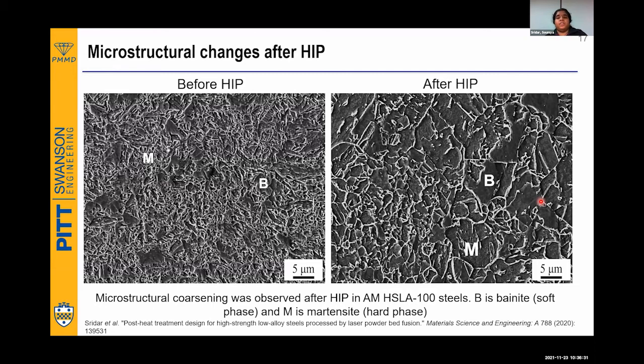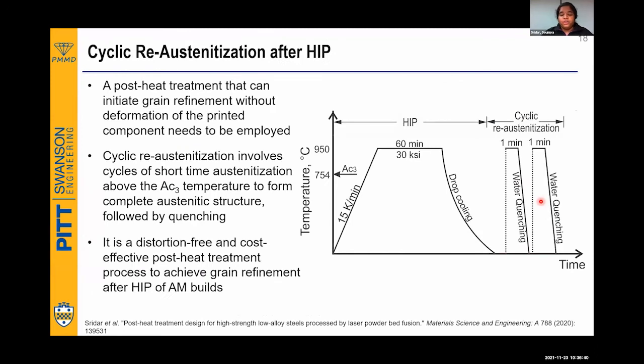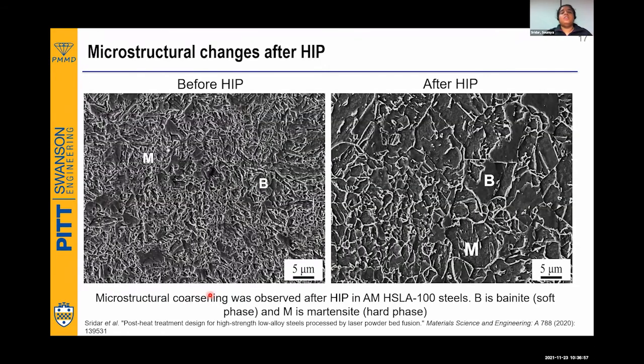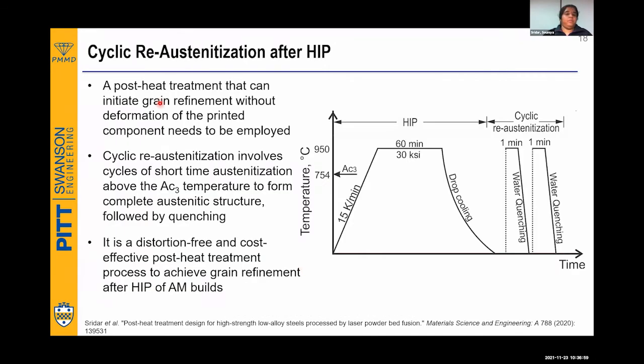So this is the reason why I'm emphasizing that this is spoiled and so on. How am I going to bring it back? That spoiled microstructure from the spoiled microstructure after HIP is this process called cyclic re-austenization. So this is a post process where I have to do a grain refinement. As I mentioned here, there is microstructure coarsening or grain coarsening. So what I have to do now is a grain refinement.